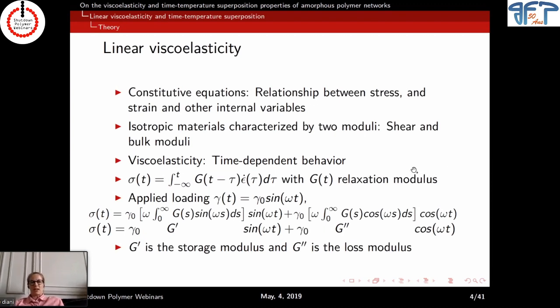And in linear viscoelasticity, that means that you can define the stress-strain relationship as such, with g of time, the relaxation modulus. And the goal is to define this function. So what do we do? Usually we apply dynamic loading, sinusoidal loading. So for example, a strain defined by an amplitude, gamma naught, and angular frequency, omega. And we're going to measure the stress.